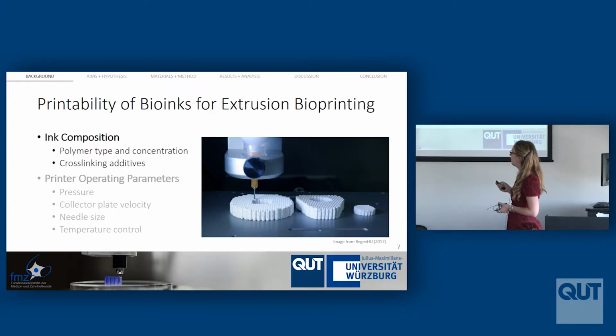And so the first is regarding its composition. So the type of polymer we used, I mentioned synthetic or natural-based polymers, and also their concentration are absolutely key. And these can have massive impacts on the biocompatibility as well. But in terms of the printability of it, we want to make sure that these are all absolutely successful so that we're getting a nice, beautiful fiber that you can print into any shape and size, as you see here. And then cross-linking additives. So this is applying UV light or those different chemicals that you add that makes that bioink mechanically robust after the process.